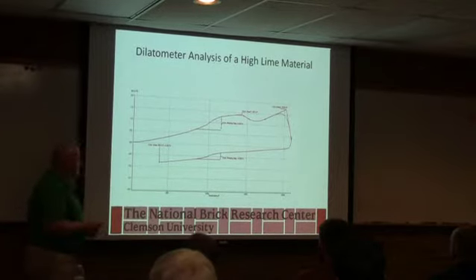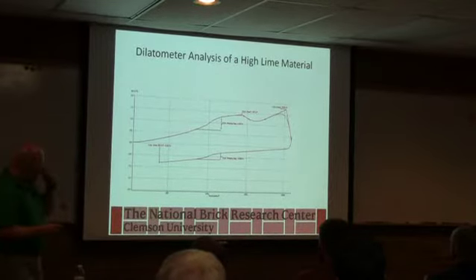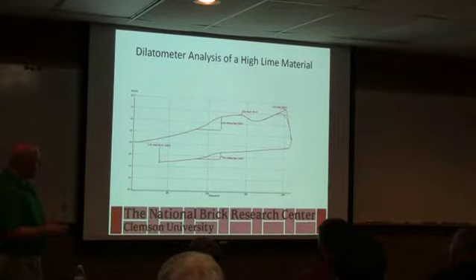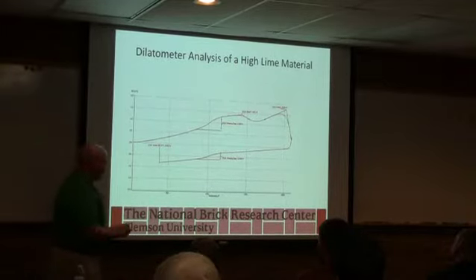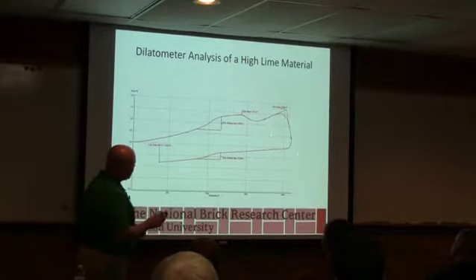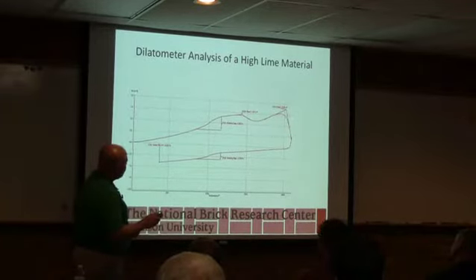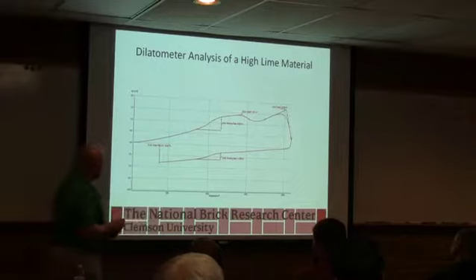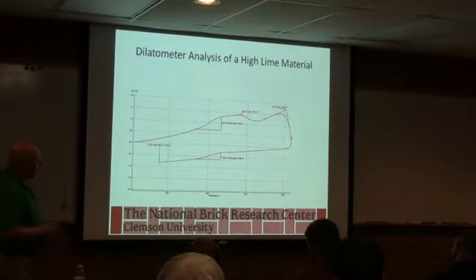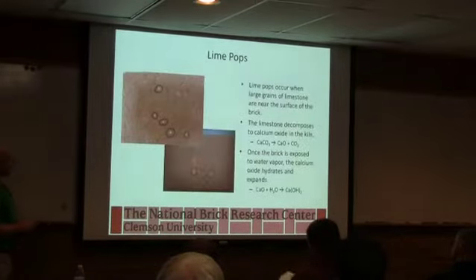But if you have a very high lime content like they do, and they're probably 15-20% calcium in that material, you've got to be extremely careful, because you can make a puddle instead of making a brick because of that reaction that takes place. So something you have to be aware of with limestone. Generally, if it's just a few pieces causing a pop, you're nowhere near that limit.